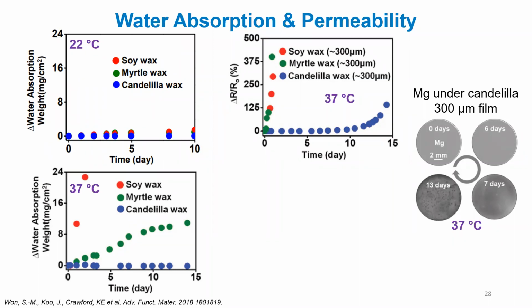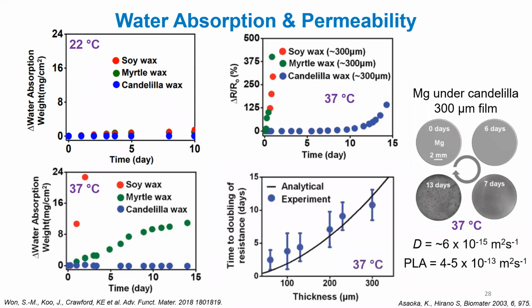And what's nice is that when you're looking at the change in resistance compared to its original resistance, the candelilla starts to increase around 7 or 8 days, which matches very nicely with the visual image, where it starts changing color around 7 days. And then, by 13, the resistance is just shooting up really high. We did another thing, looking at the time to doubling of the resistance. And then we did an analytical model of what this should look like. And then we estimated from that what the diffusion coefficient should be.